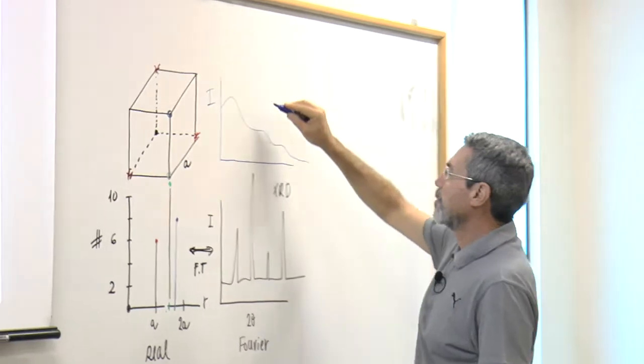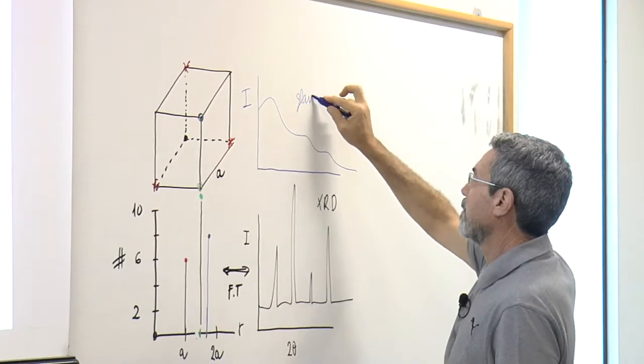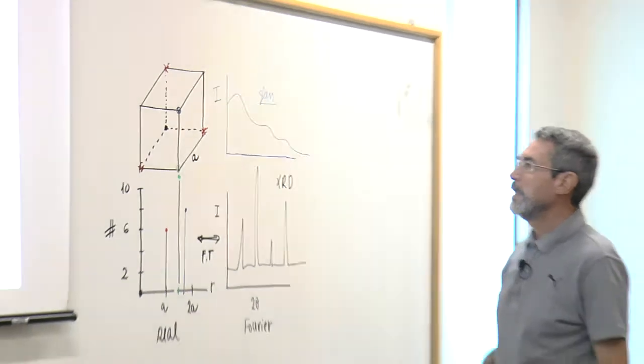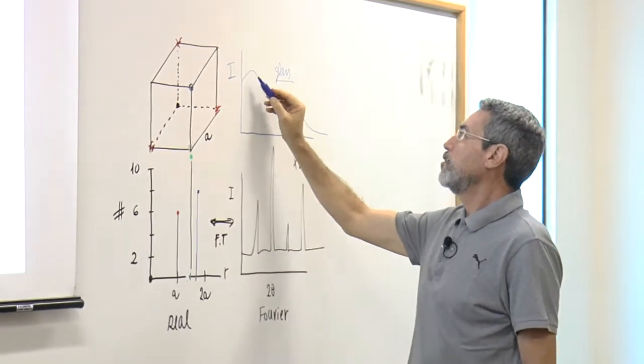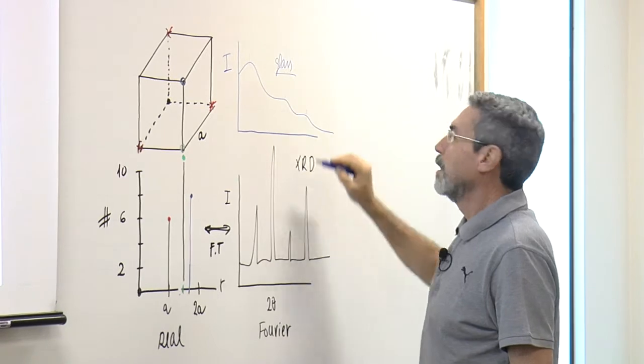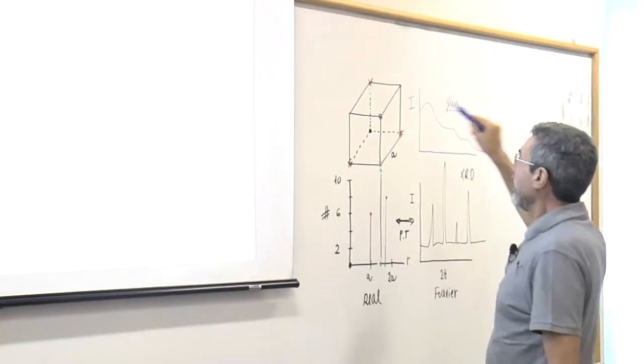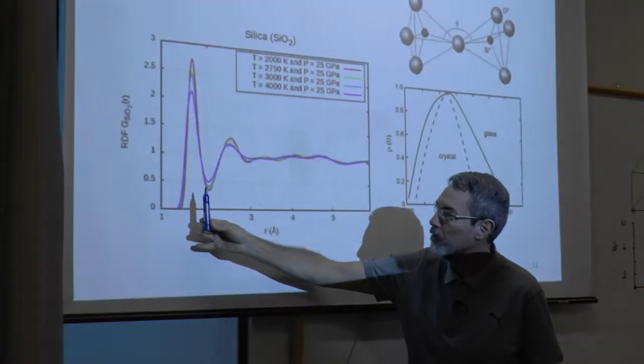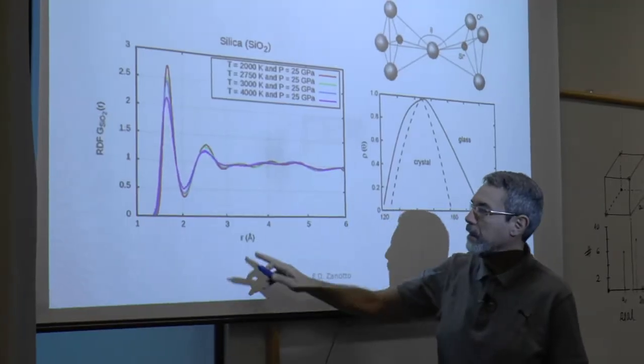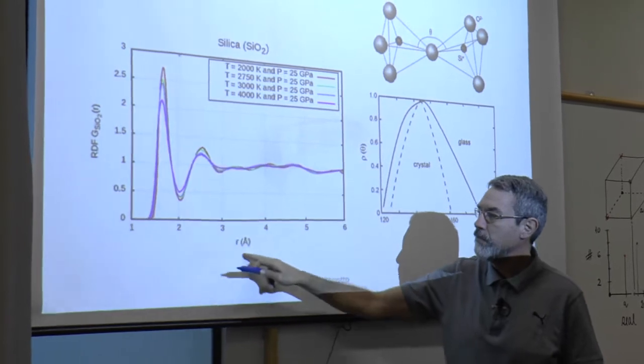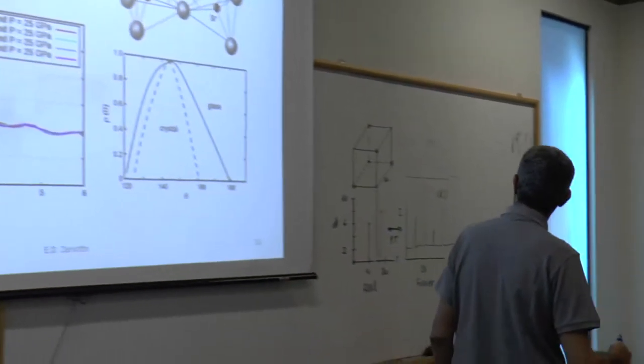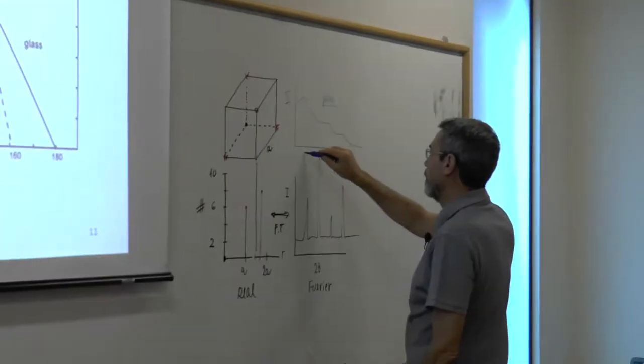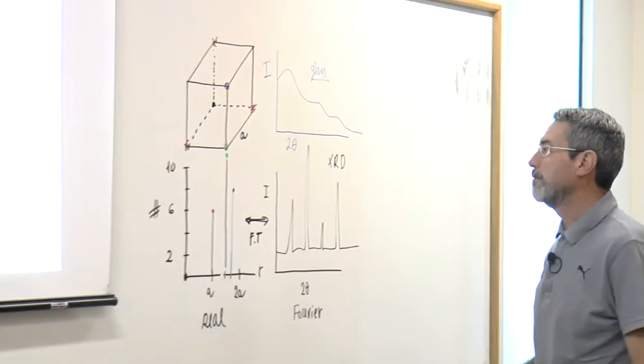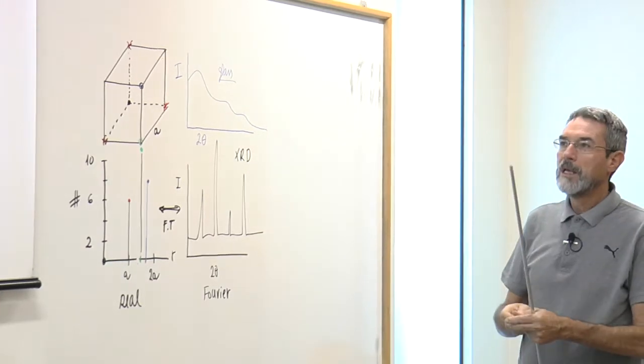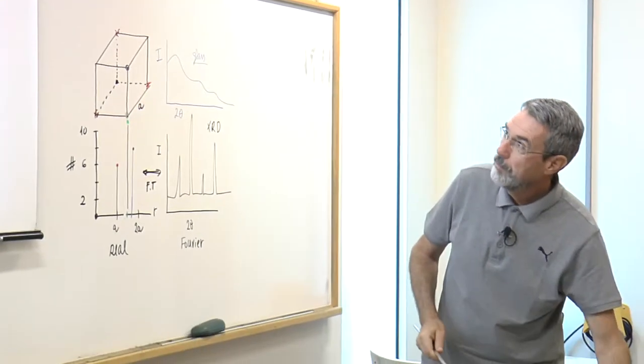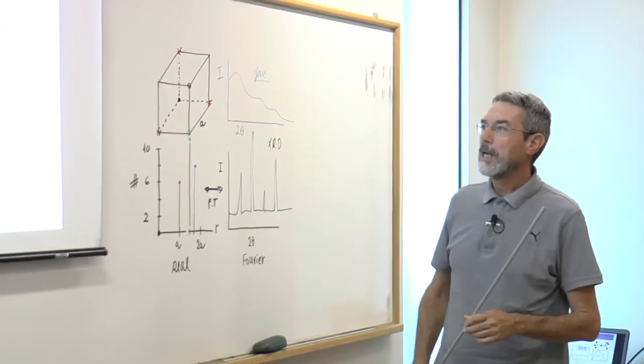This is the XRD spectrum of a glass, and this is for a crystal. And these peaks here are related, after we Fourier transform, to this one and this one in real space. This is real space already, so it has been Fourier transformed. And this is the diffraction angle 2 theta. Silica glass.